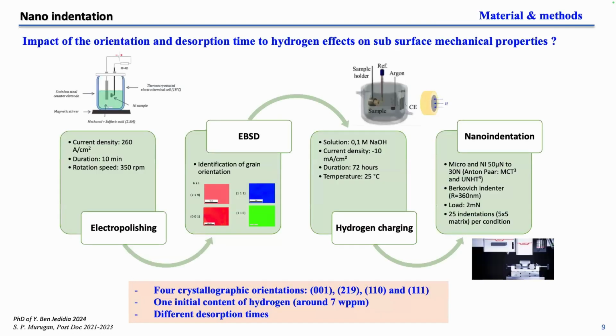Now we try to check the effect of these results on indentation, so we perform indentation on different surfaces, with specific surface preparation. We perform nano indentation with a pre-charging situation, just after. We perform the first indentation 20 minutes after the charging condition.